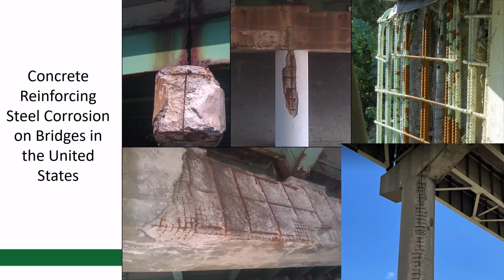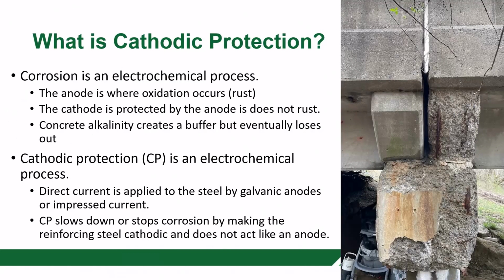And here's another example. This is a shotcrete repair. You can see the welded wire mesh that's been put into the repairs, and they didn't chip behind the bars and do a lot of good practices there, and they didn't really address the corrosion issue with the repair. And this is just an example of a typical one, this is in Kentucky at the Sherman-Minton Bridge. So just examples, and you guys will see these every day. So what I wanted to focus on is one of the solutions potentially to help deal with structures that actually have problems at this point, active corrosion.